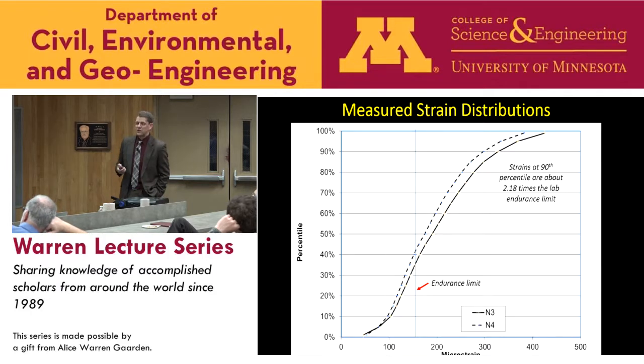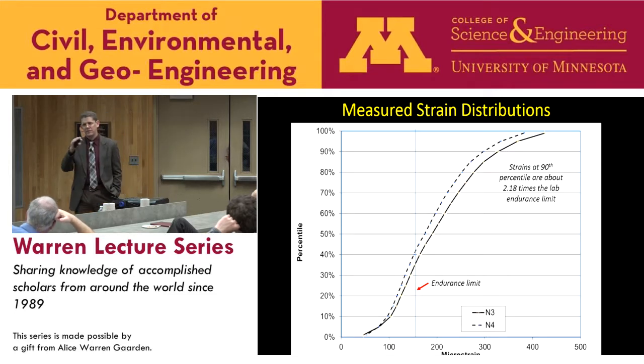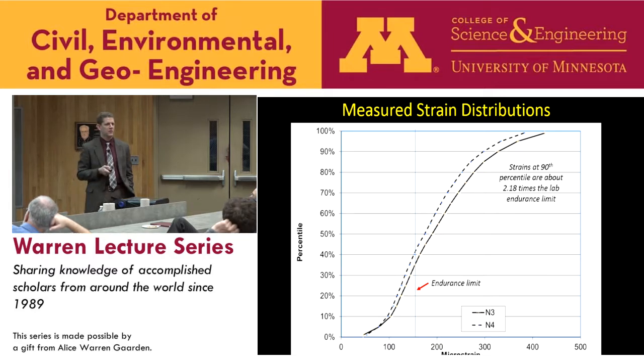Okay, so we also embedded strain gauges in the pavement. We measure the in situ strain over time, and we can look at the cumulative distribution of strain. What I've got here is the cumulative percentile and the microstrain. For example, the 50th percentile strain for the two sections was around or just under 200 microstrain.